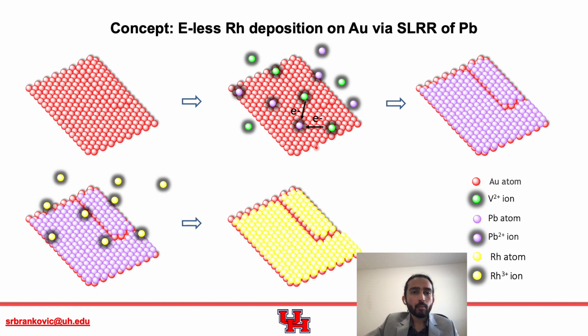So as shown in these schematics, we start with a gold substrate and then we expose this gold substrate to solution which contains lead and vanadium ions. So vanadium ions serve as a reducing agent for lead and we end up with a lead monolayer on the gold substrate. Now, this lead monolayer on a gold substrate is exposed to the aqueous phase solution which contains rhodium ions. And during this step, we have SLRR reaction and then results as a rhodium monolayer on top of gold. And this cycle could be repeated several times to get higher thickness of the rhodium on top of the gold.